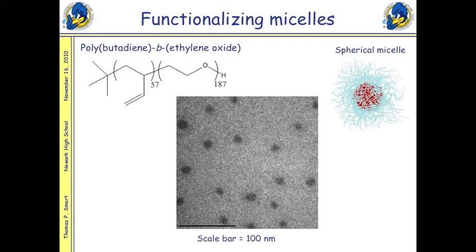And so you add a precise amount of your initiator, and then you add a precise amount of your monomer units, and each one of the initiators, a chain grows from that until you run out of the butadiene units.